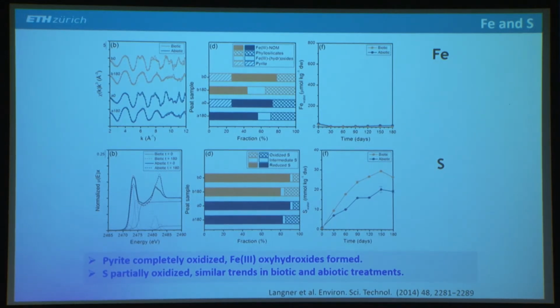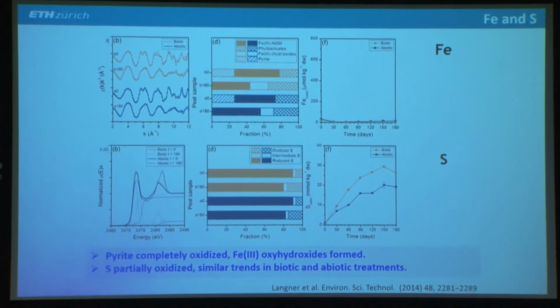It was actually surprising. For sulfur, we also observed a little bit of oxidation. So there was mainly reduced sulfur in these samples, and this is derived from sulfur XANES spectra. This is a typical sulfur XANES spectrum in which you see here at the lower energy mainly the reduced sulfur, and at the higher energy the oxidized sulfur groups. And you can then follow how much reduced and oxidized sulfur there is, and you see a little bit of oxidation of sulfur. You also saw some sulfate forming that went into solution, but it was not completely oxidized.